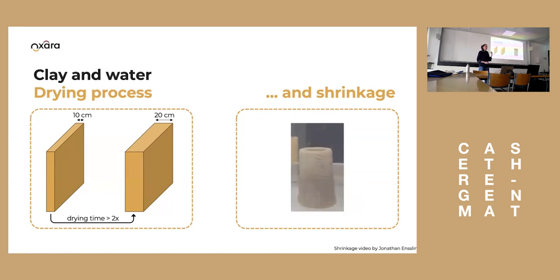And this is, of course, a very extreme case when you have only clays and not sand and not gravel, which reduce the shrinkage. But yeah, earthen materials have shrinkage. And this is because if the water withdraws, also these capillary bridges pull the material together. And it's important to keep it in mind for earthen construction.